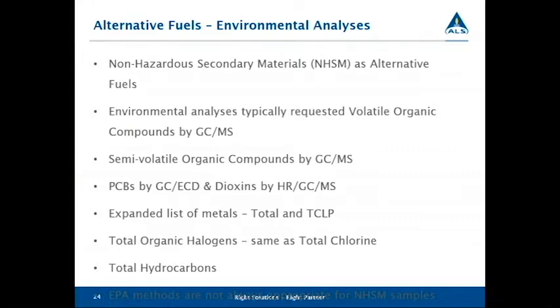For the non-hazardous secondary materials, there's typically a set of environmental analyses required. Those include volatile organic compounds by GCMS, semi-volatiles by GCMS, PCBs, dioxins. There's an expanded list of metals for both total and TCLP. And then we also do the total organic halogens. It's the same as the chlorine test that we use for the fuel. And then also total hydrocarbons. This list can vary depending on the material that's being used as a non-hazardous secondary material. It also depends on the matrix, what that fuel or material is made of.